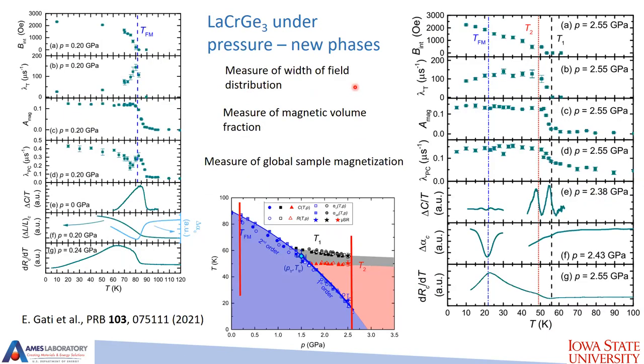Fine. Let's look again. Let's compare data for base zero pressure, 0.2 GPa, and somewhere around 2.5 GPa. Internal field from muon measurements. Internal field is some measure of magnetic moment, with the caveat that you need to pay attention. So at base temperature, the internal field is very similar. Lambda T, transverse relaxation, is a measure of the width of the field distribution. At low temperatures in the purely ferromagnetic phase, it's very low. It's broad both in the new phase and in the ferromagnetic phase at 2.5 GPa.